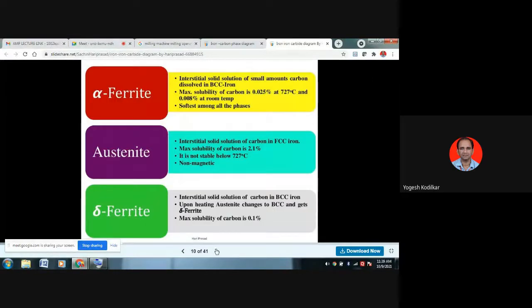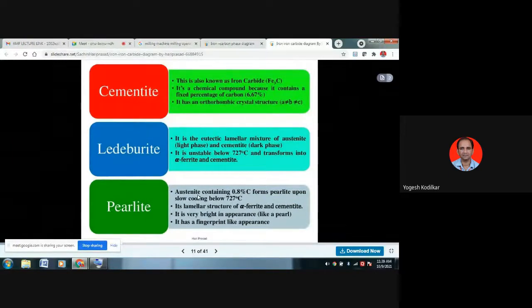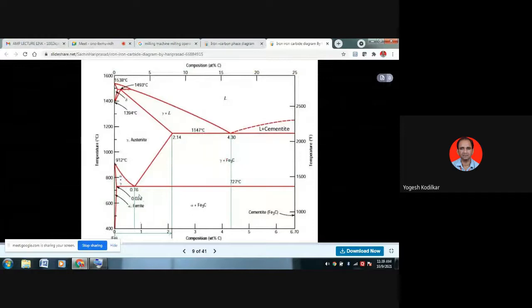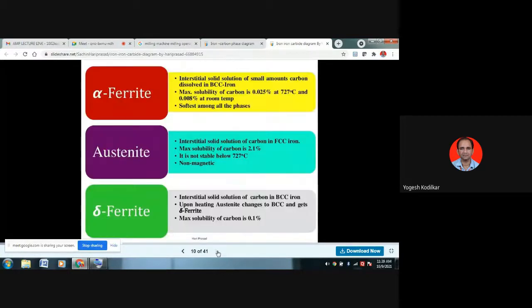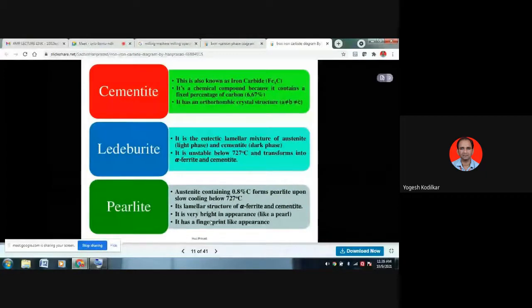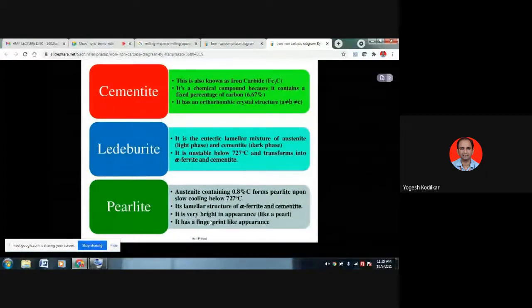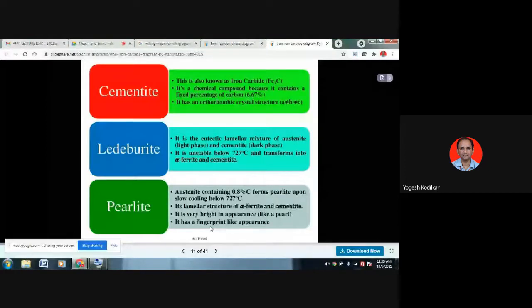That is the ledeburite phase, and the last phase is the pearlite phase. Austenite containing 0.8 percent carbon forms pearlite upon slow cooling below 727 degrees Celsius. So this is the pearlite phase, and below 727 degrees Celsius, initially there is a pearlite phase. Pearlite has a lamellar structure of alpha ferrite plus cementite. It is very bright in appearance, like pearl. That's why the name is pearlite phase. And it has a fingerprint-like appearance. Okay.